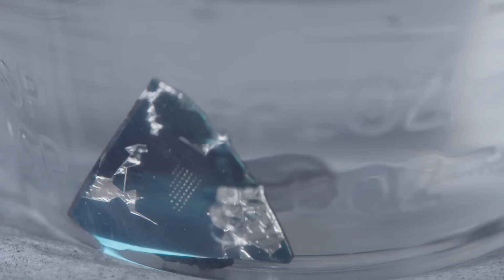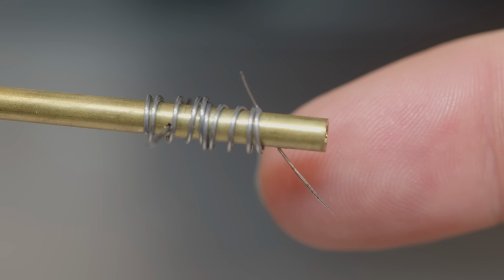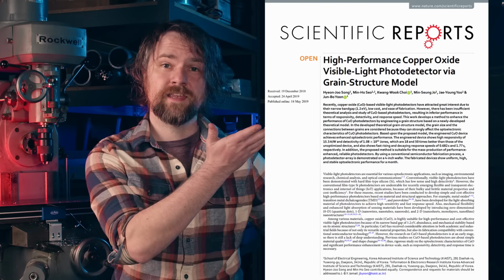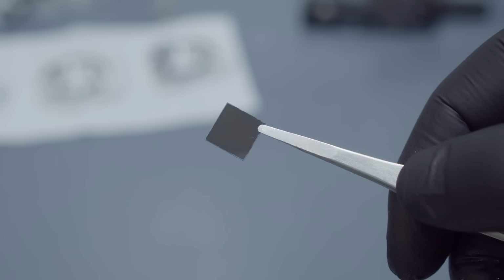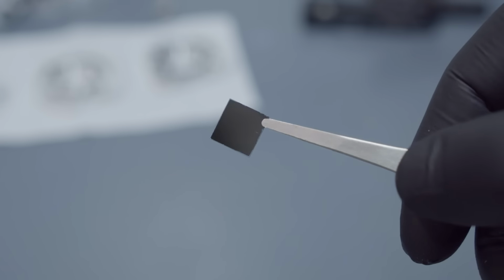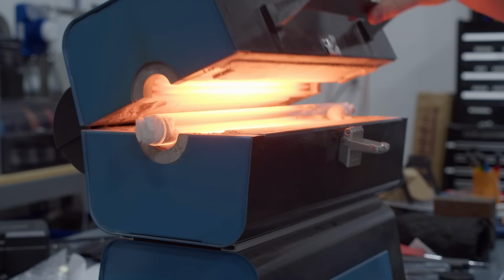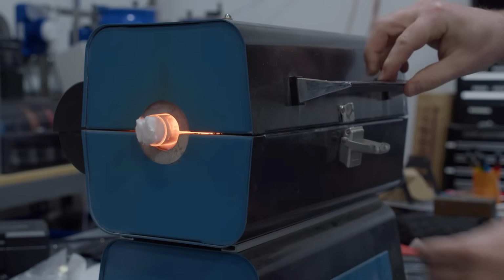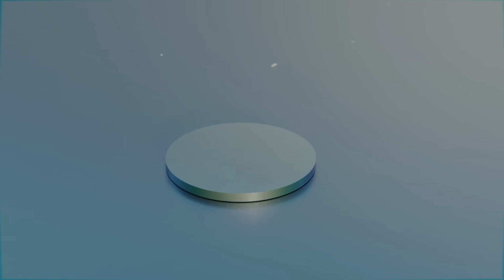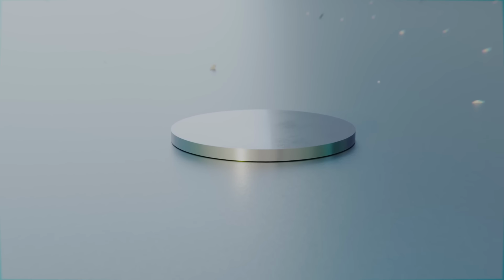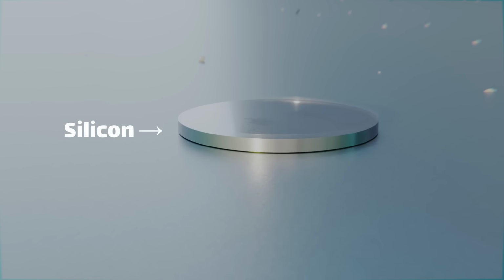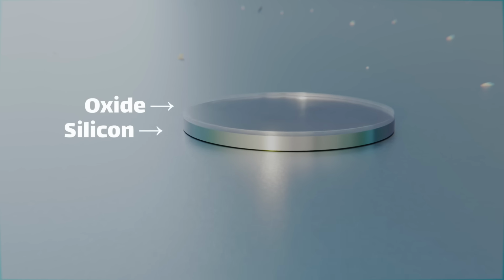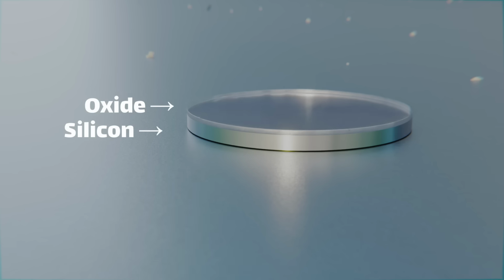This will be a good test of both the semiconducting layer and the necessary extra bits like depositing electrodes and probing the resulting circuit. To actually grow the oxide, I'm following a thermal oxidation protocol from this Nature paper. First, we take a silicon substrate and grow a thick layer of silicon dioxide on top, which is done at 1,000 degrees in a furnace. We need to grow this oxide so that there is a physical barrier between the experiment and the underlying silicon. It would be pretty silly to go through all this effort to make a copper oxide device and then realize we were actually measuring the silicon substrate instead.